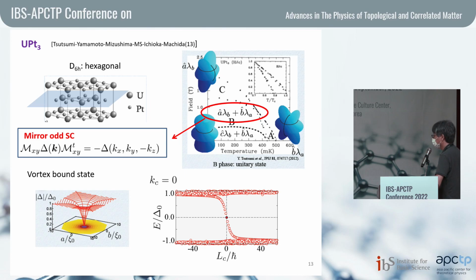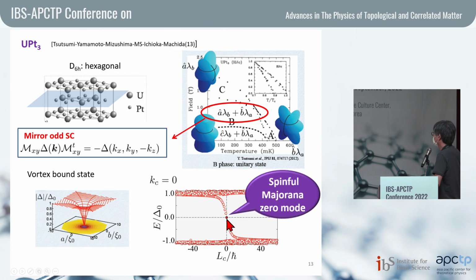And here I show the spectrum calculated by Tsutsumi-san. Here I consider this particular mirror invariant momentum. This is the spectrum that comes from the bulk spectrum. In addition to this one, we also have a mini-gap state inside the vortex. And as you can see, we have a zero energy mode. This is actually the spin-full Majorana zero mode. So in this case, we can nicely obtain the spin-full Majorana zero mode.